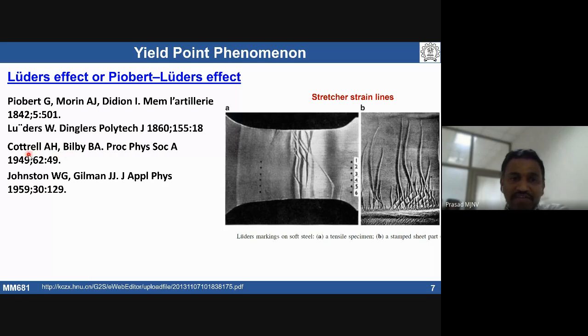This is the kind of thing they used, using Cottrell atmosphere. Presence of solute atoms can interact with the dislocations and can lock the dislocation movement, and after that unlocking can take place. That's the kind of thing they explained, by Cottrell and Bilby.